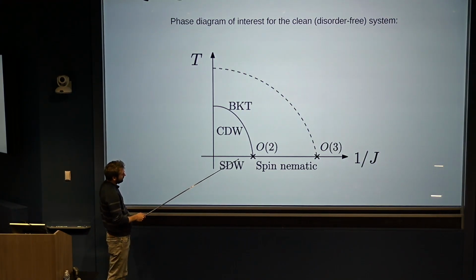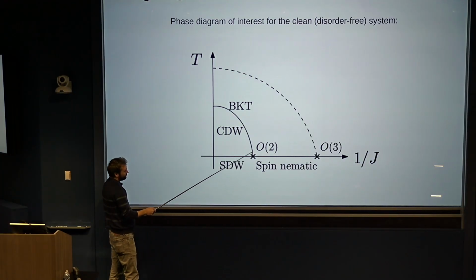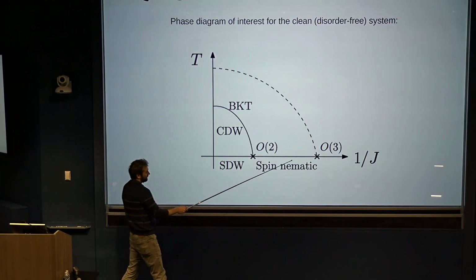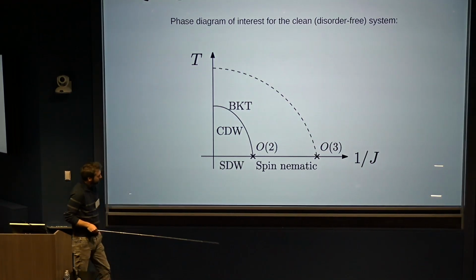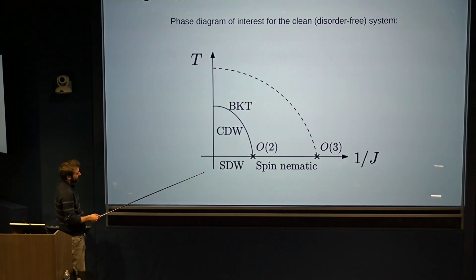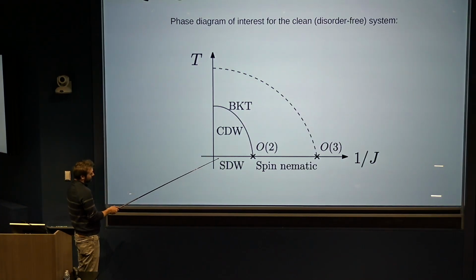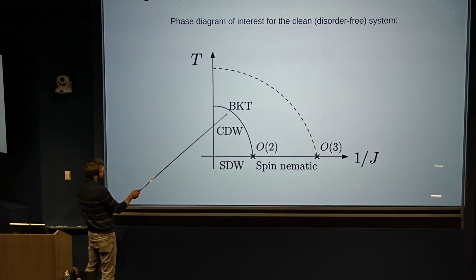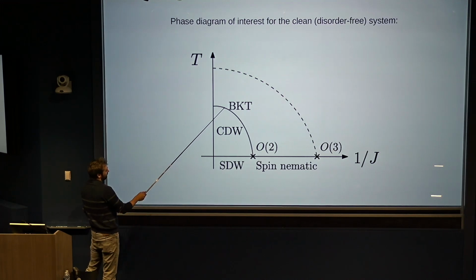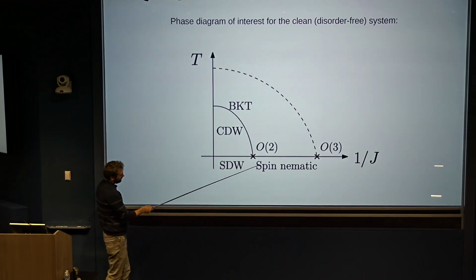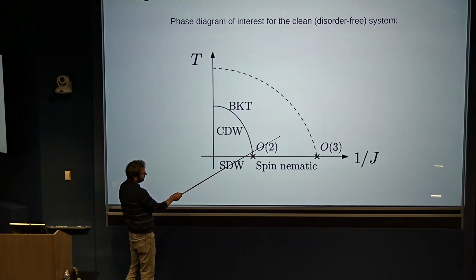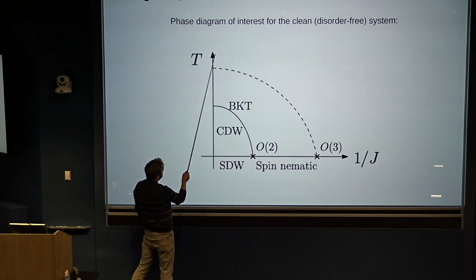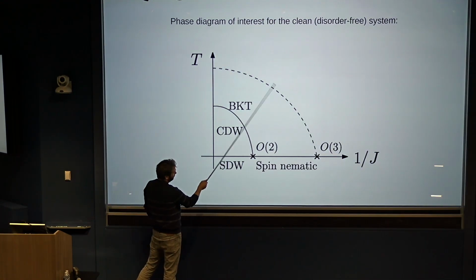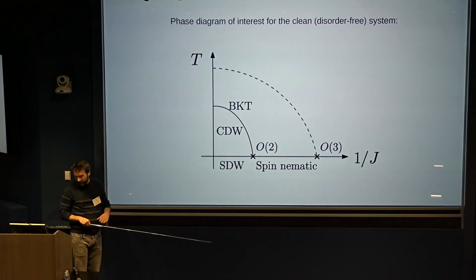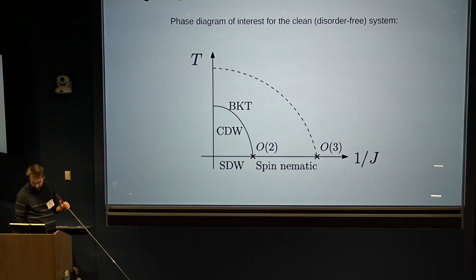And so these two phase transitions are in the O(2) universality class if you assume an incommensurate charge density wave, and the O(3) universality class. And as you raise the temperature, as this is a 2D system, the magnetism goes away at any finite temperature, and the spin stripe becomes a charge density wave. If it's incommensurate, at higher temperature it will go away via a BKT transition. And then here the spin nematic order disappears at any non-zero temperature. And this dashed line is a crossover region, which is the onset of local spin nematic order. So that's the clean phase diagram. That's not a new result.